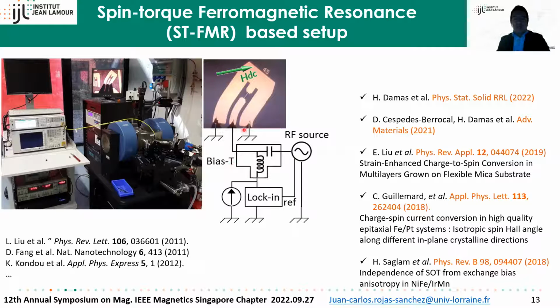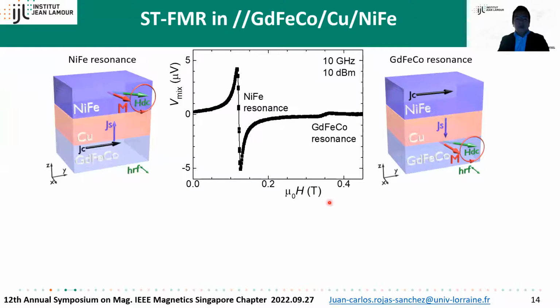This is our setup. We have our slab here. We inject a radio frequency current, and we also add a DC bias current, and we use lock-in detection. Our main sample is this trilayer: 10 nanometers of gadolinium iron cobalt, 4 or 6 nanometers of copper, and 4 nanometers of permalloy, capped with aluminum. We can observe both lines far from each other, so we can analyze them individually: the resonant line of permalloy and the one of gadolinium iron cobalt. So this is based on ferromagnetic resonance.